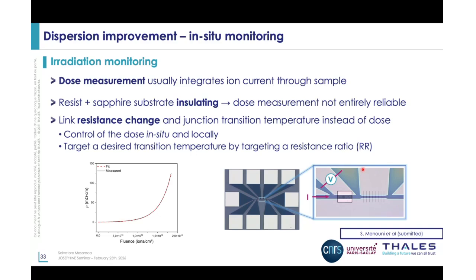So we came up with another way of checking the amount of defects that we create inside of these devices, and it's by in situ and in real time measuring the change of resistance during the irradiation. To do that, we have these devices here that you see at the bottom right. It's something that we call the irradiation monitoring device. It's because we have just a bridge where at the center we have our 8 junctions, which is our way to simulate a SQUID in a way, or anyway to control the quality of the junctions made.